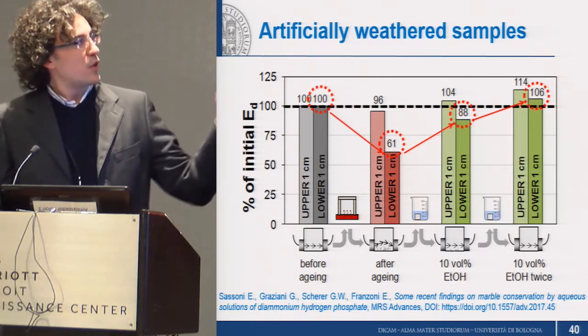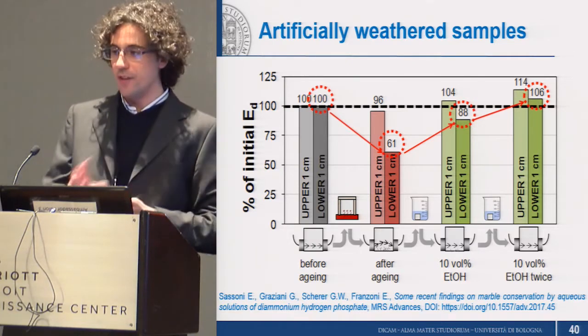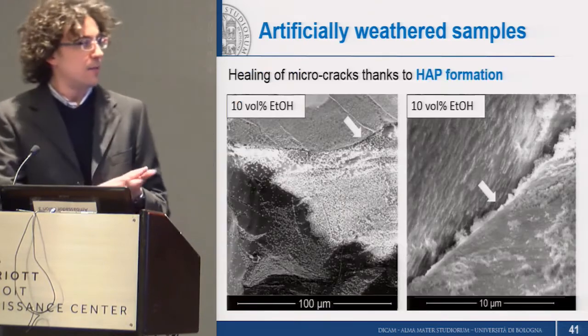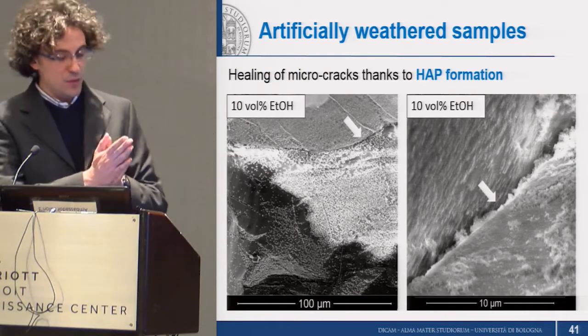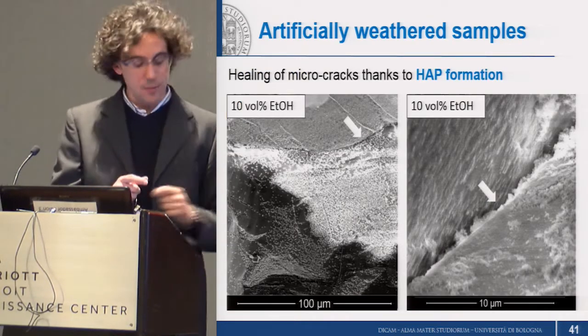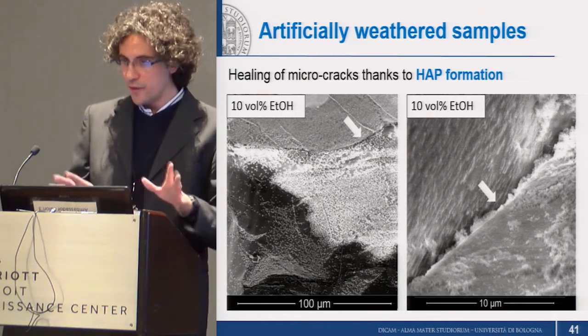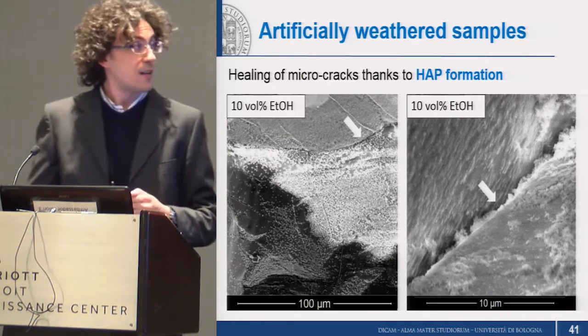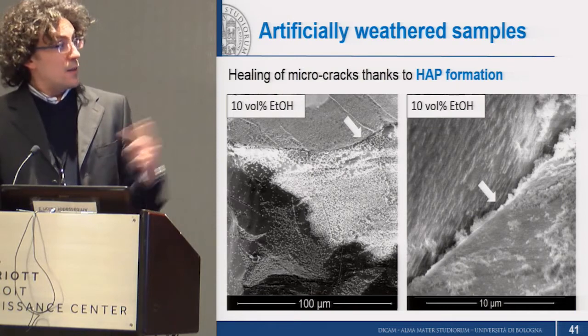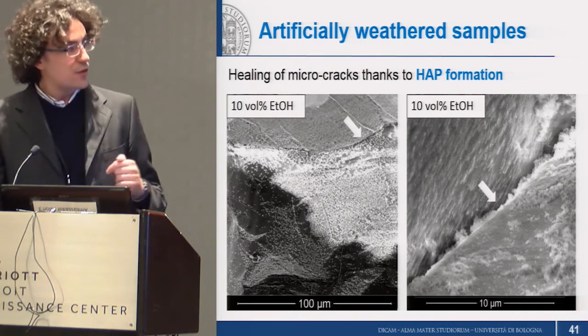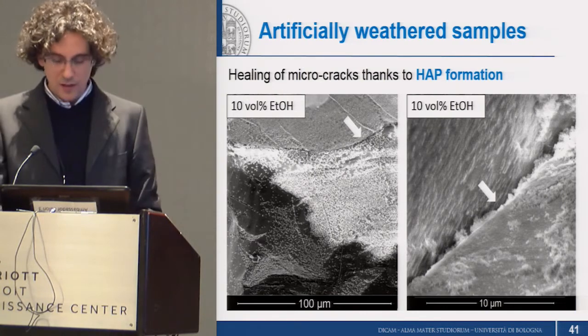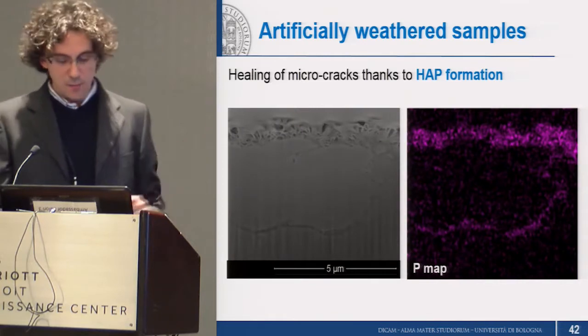This was made possible by the formation of the new mineral, HAP, inside the micro cracks between grains. So this new mineral was able to bond the grains and improve mechanical properties, as you can see also from this FIB cross-section, where you can see the new phases forming inside the microcracks between the grains.